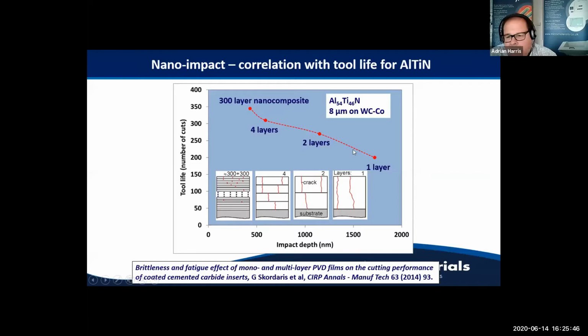failure. At the other end of the scale, we just have this one monolithic layer of coating material. There's no interface present other than the interface with the substrate. And yeah, there's a question coming from somebody there.